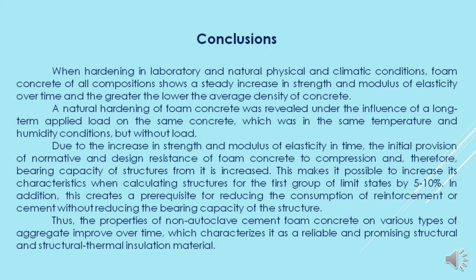Due to the increase in strength and modulus of elasticity in time, the initial provision of normative and design resistance of foam concrete to compression and, therefore, bearing capacity of structures from it is increased. This makes it possible to increase its characteristics when calculating structures for the first group of limit states by 5 to 10%. In addition, this creates a prerequisite for reducing the consumption of reinforcement or cement without reducing the bearing capacity of the structure. Thus, the properties of non-autoclave cement foam concrete on various types of aggregate improve over time, which characterizes it as a reliable and promising structural and structural thermal insulation material.